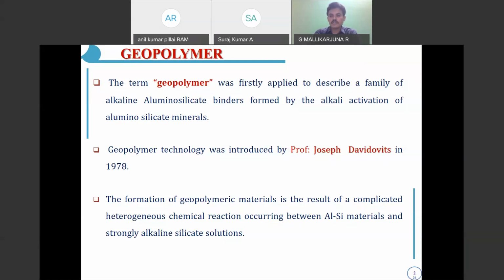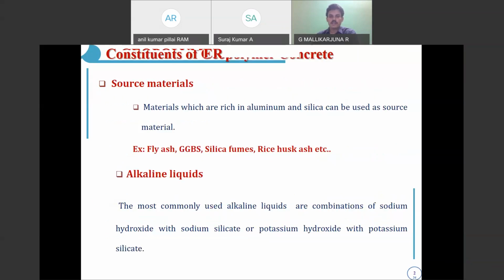It is completely different from the normal hydration process. Whenever we add water to cement, it gives CSH gel plus Ca(OH)2. But here we completely replace the cement with fly ash or GGBS, and water with alkaline activators such as sodium hydroxide, sodium silicate, and potassium hydroxide and potassium silicate. Those are activated with these alkaline activator solutions, and by that activation, we get the chemical mechanism as a polymerization process. I'll explain these things in detail.